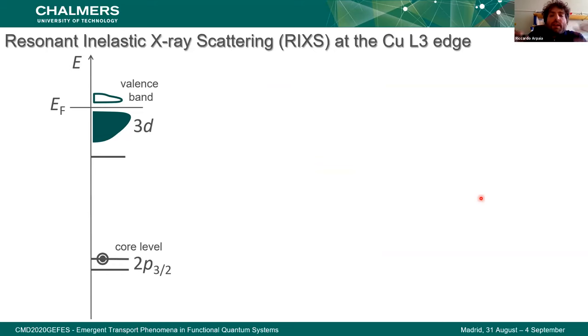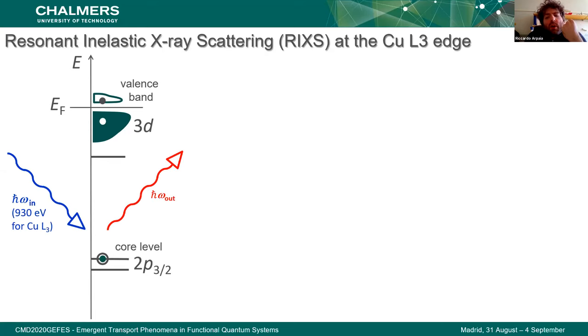For those who are not familiar, let's start by discussing in more detail resonant inelastic X-ray scattering, in particular the copper L-edge, where measurements on YBCO are performed. RIXS is resonant because the energy of the incident photon is chosen to coincide, and so to resonate, with one of the atomic X-ray absorption edges of the system. The RIXS event can be thought of as a two-step process. The incoming X-ray excites an electron from a core level into an empty valence band. Then the empty core state is filled by an electron from an occupied state under the emission of an X-ray.